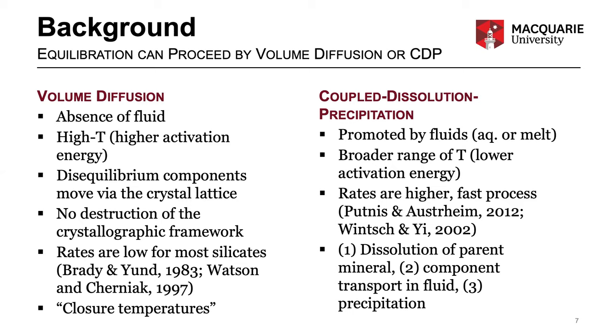coupled dissolution precipitation is very fast. And it involves these three steps of dissolving, transporting over very tiny scales to quite large scales, and then precipitation. The scales of transport are likely important in whether the age of the domain is reset or not.